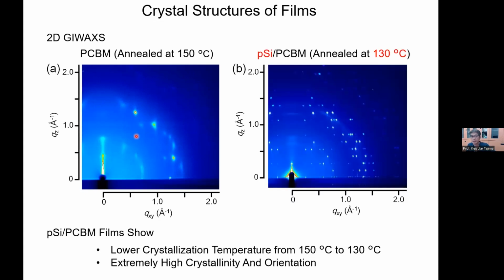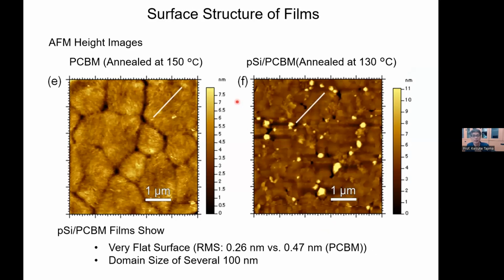But what we found here is that when you put this surface segregated monolayer on top of the film, first, the annealing temperature gets lower: at 130 degrees it crystallizes. At the same time, you can see lots of diffraction spots, totally different from the pristine PCBM. It's extremely high crystallinity, and just by looking at this diffraction you can tell there's a very good orientation of the crystals inside the film. We analyzed this pattern to get some idea of the crystal structure. But first, let me show you the AFM surface image.